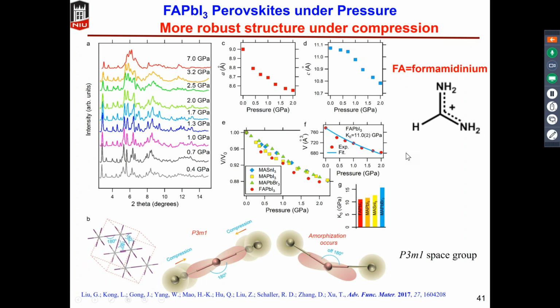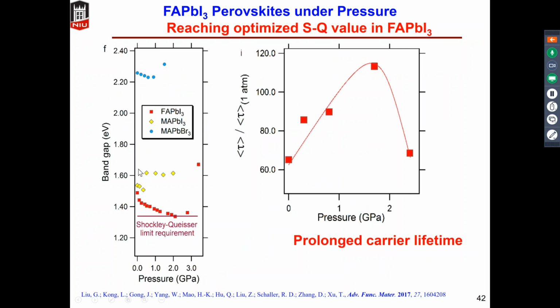However, the band gap actually decreases all the way to reach the Shockley-Queisser limit. We know that the efficiency of single junction solar cells is limited by the so-called Shockley-Queisser limit. So there's some optimized band gap, which is about 1.38 electron volts. So by compression, we can actually push down the band gap of FAPbI3 all the way to this optimized Shockley-Queisser band gap. And meanwhile, we also notice the carrier lifetime increase during this compression.